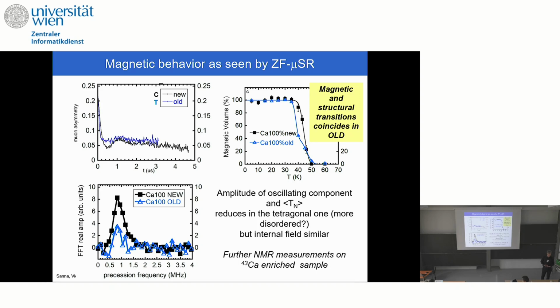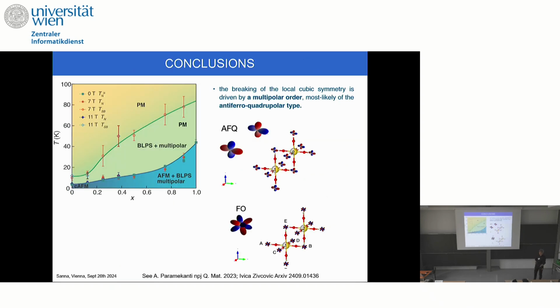So now, ferro-octupolar or antiferro-quadrupolar, I don't know exactly how to give you a reply about that, but this is an experimental evidence of the magnetic response in tetragonal and cubic structure, which I think we should consider, and it warrants further investigation. So these are my conclusions. The breaking of local cubic symmetry is driven by multipolar order, most likely of the antiferro-quadrupolar type, at least in this part of the phase diagram.